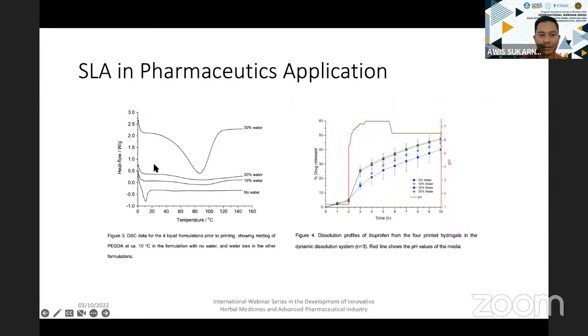But when you look at the DSC, you can see here that with 0 and 20%, the melting point of the polymer doesn't really show, but at 30% of water here, you can see there is a very big peak. So this one is actually because of the water.